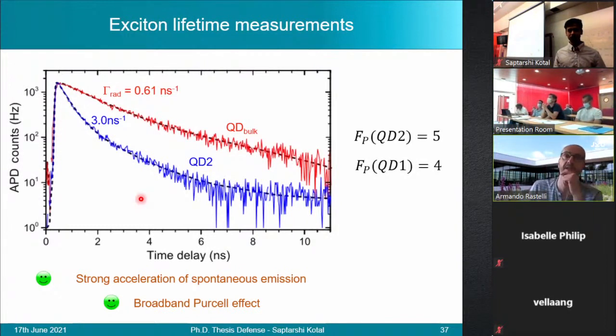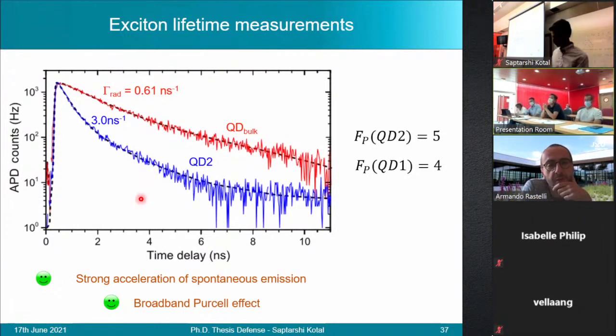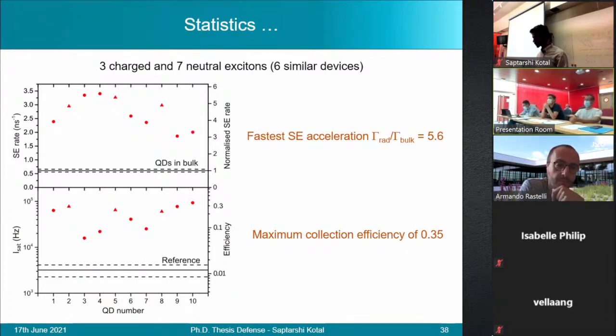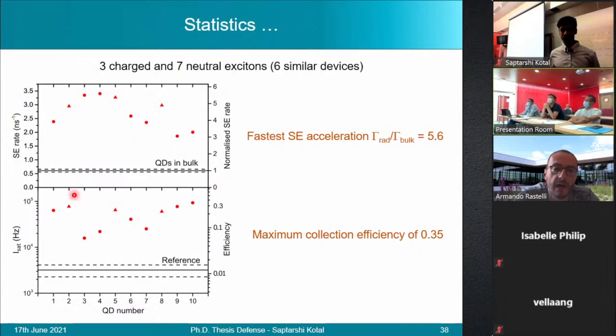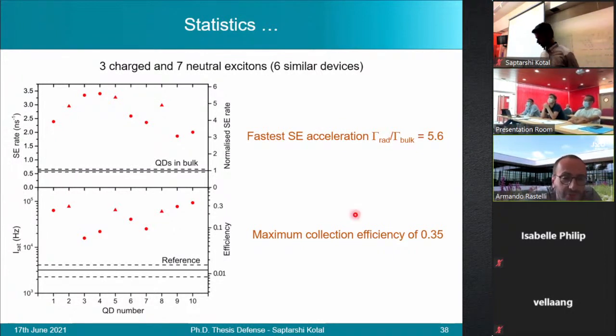Yeah, it makes sense. Did you try to correlate actually this lifetime and the saturation intensity? So you have measured, did you measure the same quantum dots? So the saturation intensity and the lifetime? Yes, here. It's the same dot that we have the saturation intensity at the bottom and the rate. These are the same. The question is whether there is any correlation between these data sets, or if they are uncorrelated.